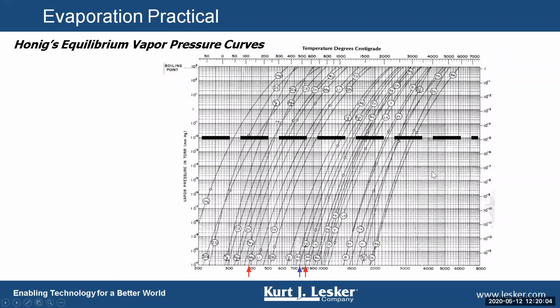Very helpful in any kind of evaporation are the vapor pressure curves. I have copies of these curves if you would like, but generally they list all the elements and give the vapor pressures of the elements, temperature in degrees C on the upper x-axis, and the vapor pressure on the left y-axis in torr. The heavy dashed line is the 1 × 10⁻² torr pressure. So if you heat a source up or you heat a material up so that it crosses this 1 × 10⁻² torr, at that temperature you will get probably good evaporation. Always a good gauge, always a good piece of information to have.